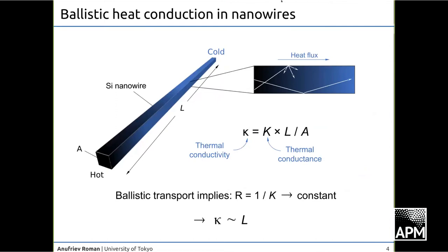That is why we are interested in studying nanowires, because a typical experiment that demonstrates ballistic conduction is to measure thermal conductivity as a function of length. Consider a regular nanowire, a simplified square-shaped nanowire with length L. By the definition of thermal conductivity, it's just conductance multiplied by the length, normalized by the cross-section. So in the case of ballistic conduction, some phonons experience no diffuse scattering on the interface, but rather specular scattering or no scattering at all.